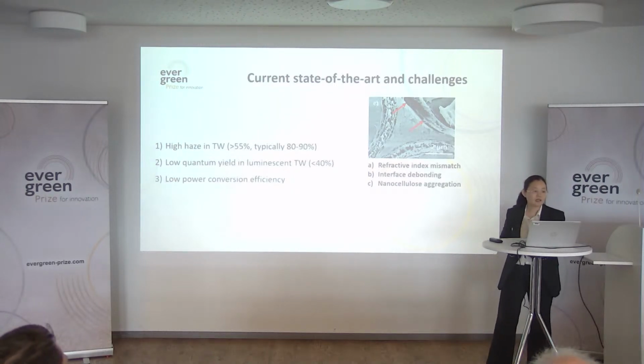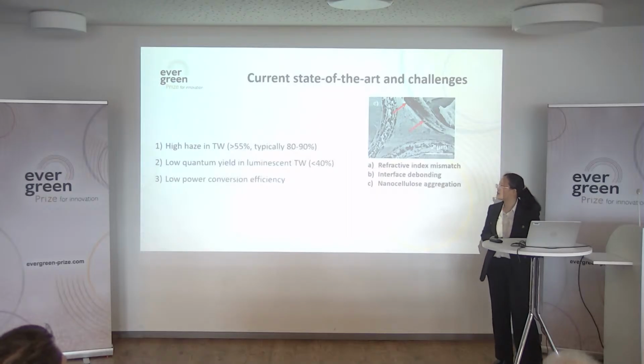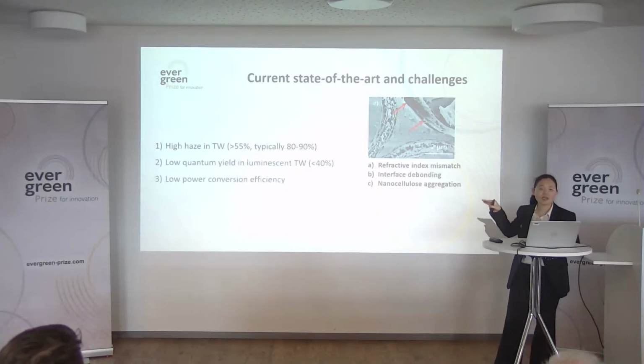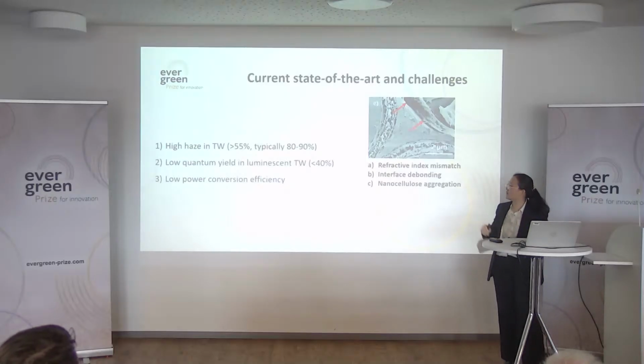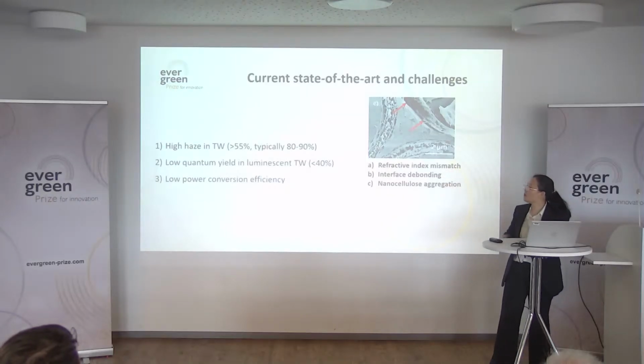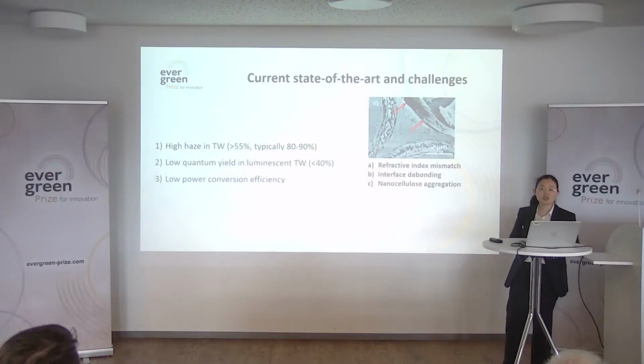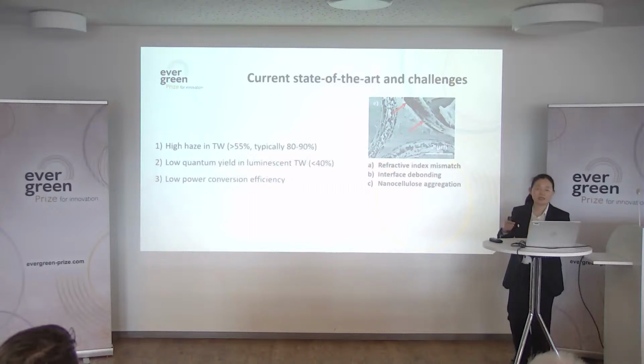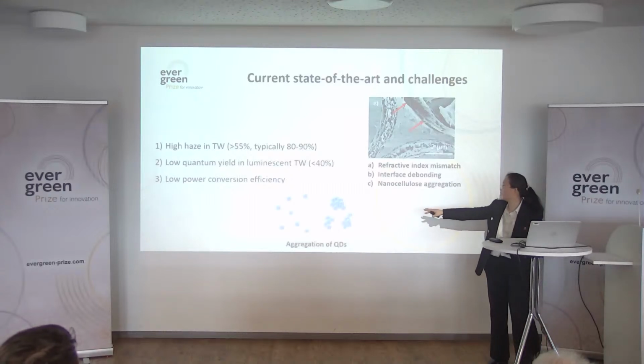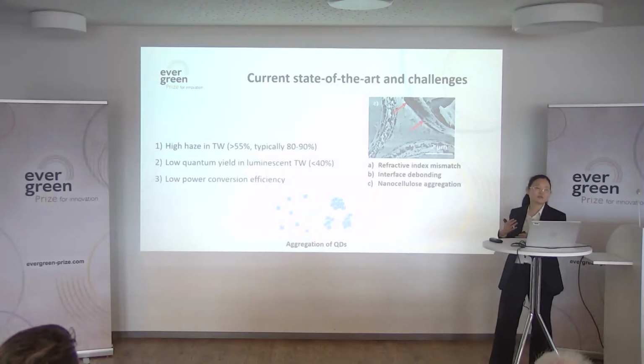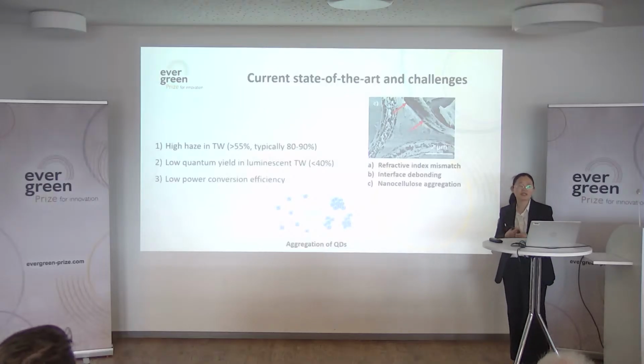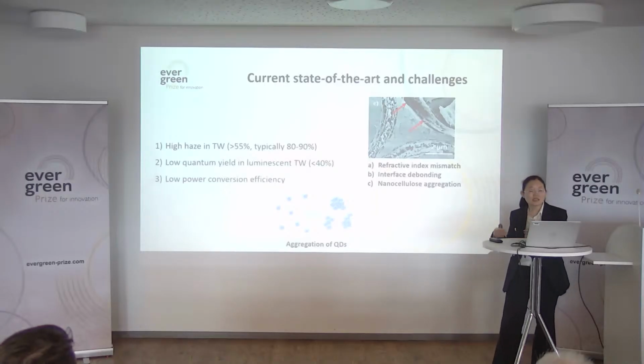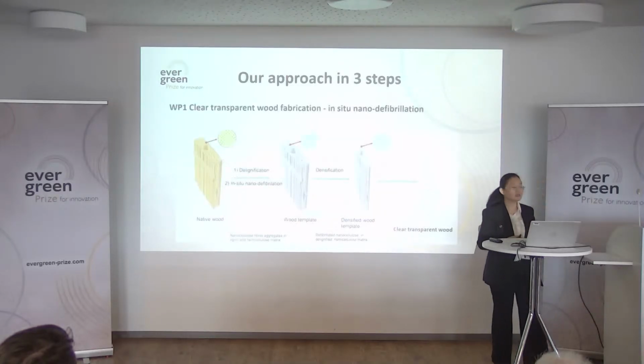And then the second, the quantum yield of a transparent wood is normally less than 40%. And from this project, we want to achieve a high quantum yield with a value over 50%. By combining the achievement of a low haze and high quantum yield, we want to enhance the power conversion efficiency of this device. And here shows one reason why luminescent transparent wood normally has low quantum yield: when we infiltrate quantum dots inside, it's really easy to get aggregation of quantum dots, which has a quenching effect, leading to the lower quantum yield. So next, my colleague Juqing will tell the details of how.